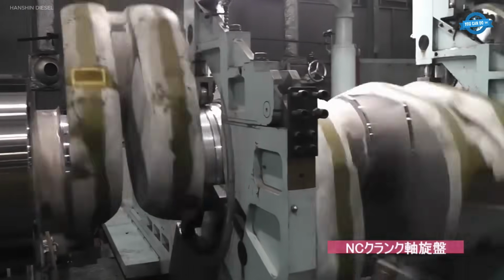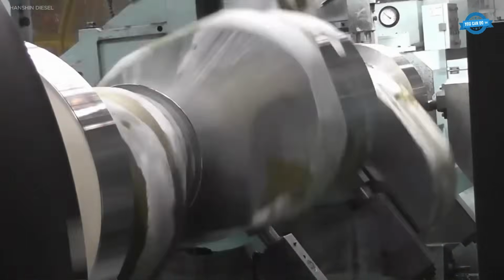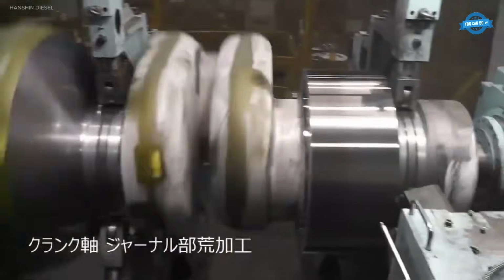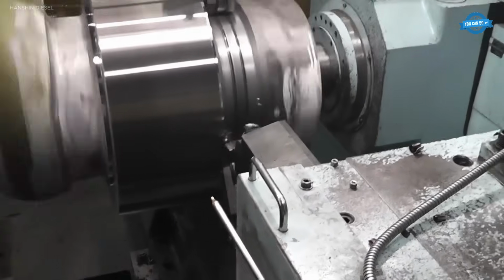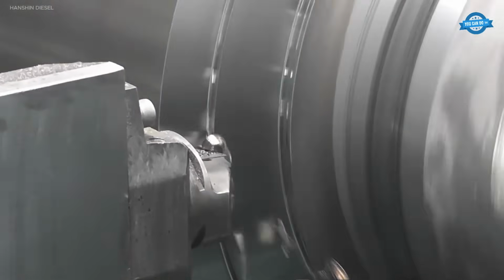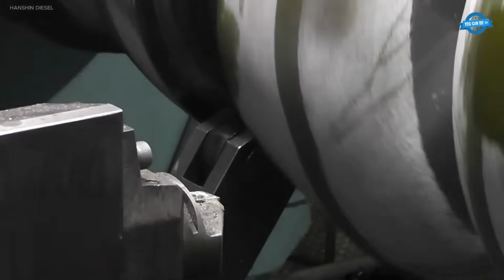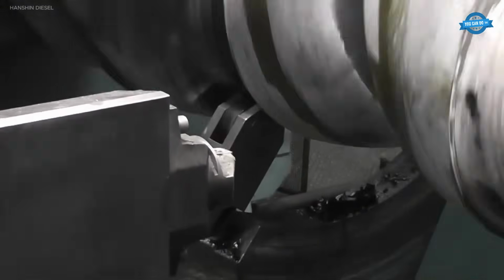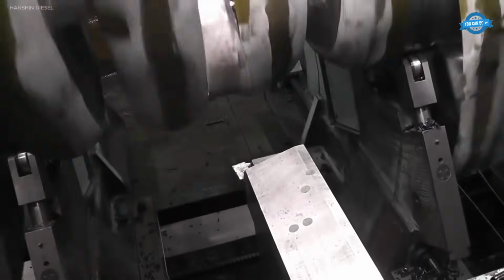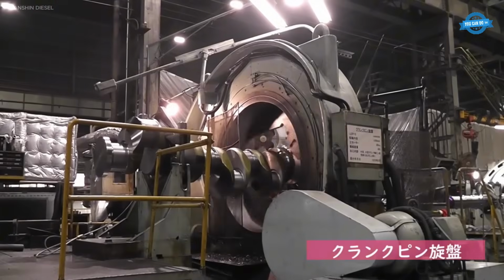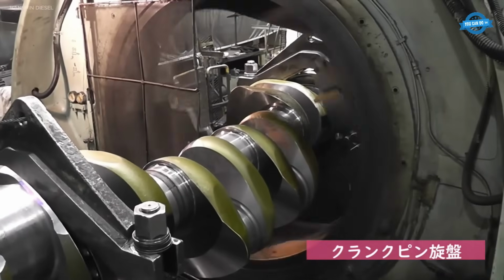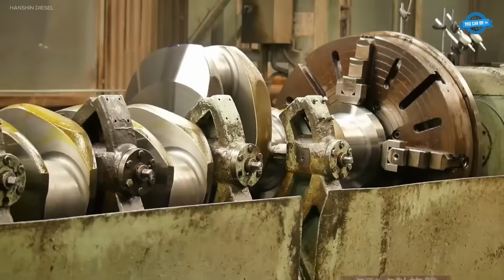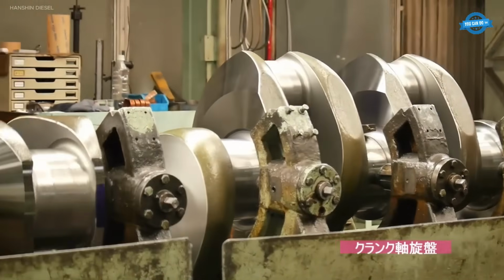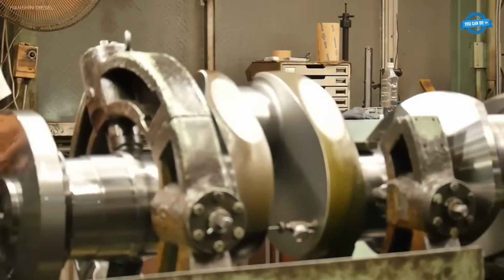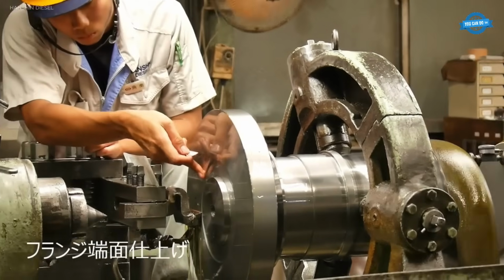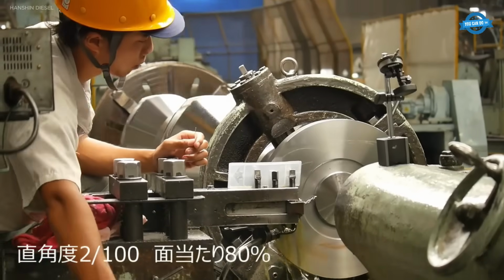Hanshin Diesel machines marine crankshafts through a closed-loop NC sequence that guarantees micron-grade tolerances. After ultrasonic inspection, the 7 meters forging enters a dual-spindle CNC roughing lathe that skims journals and crank pins to a plus 0.30 millimeters envelope. The shaft then rides inline rails to a dedicated crank pin lathe, where inner widths are finished while maintaining 0.02 millimeters / 100 millimeters squareness and 80% blue bar contact.